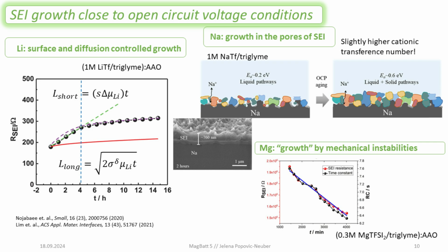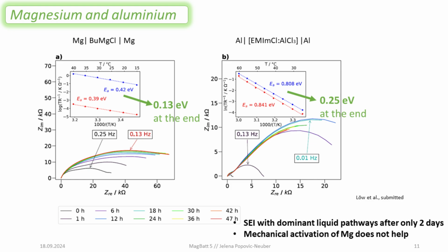And then the very initial studies on magnesium, we have only seen something quite strange, and that is that the resistance of our SEI actually drops in time. So this is a specific type of electrolyte. It's a liquid-solid electrolyte in contact with magnesium. And instead of these kind of square root t growths, we see just some kind of drop of resistance in time. And we could say, okay, this is maybe mechanical instabilities or dissolution that we already talked about. But we did not know in detail what is happening here.